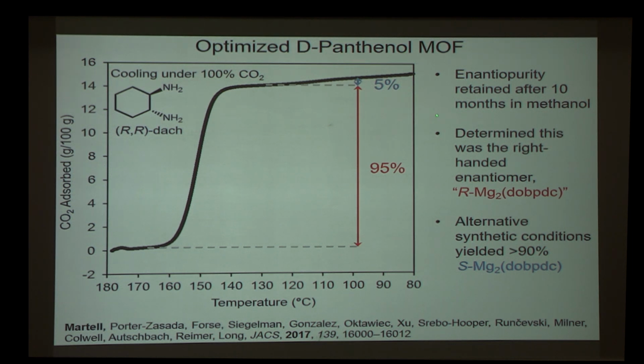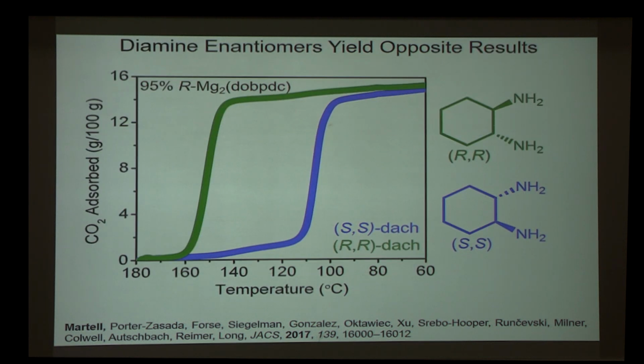So I don't have time to show you all of these experiments, but I'll show you one simple control. Here in green is the data I've been showing all along with the right-handed MOF and the right-handed diamine. But we would anticipate that if we simply used the left-handed diamine, now instead of a single step at 160 degrees, we should see one step at 120 degrees, and that's exactly what we observed. So this simple experiment provides some compelling evidence that we indeed succeeded in making a MOF that was enantio-enriched.